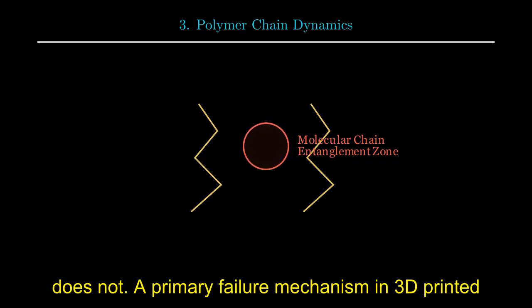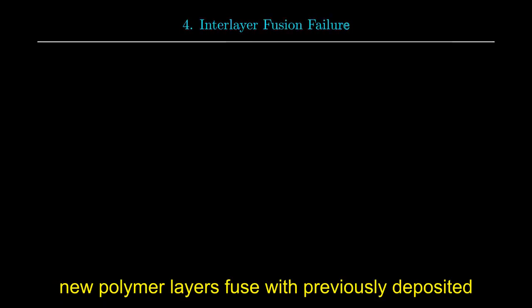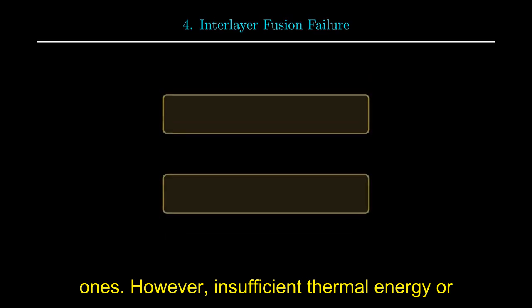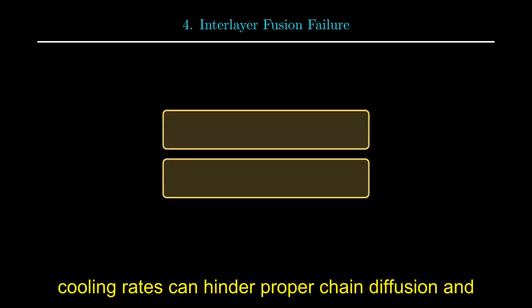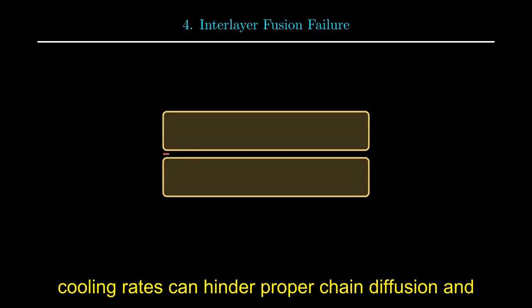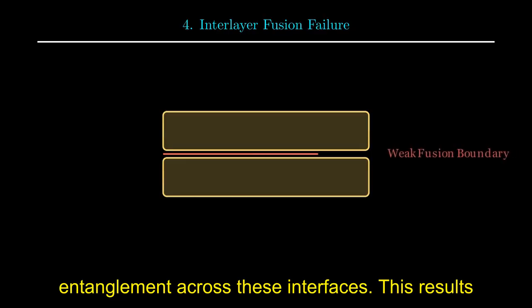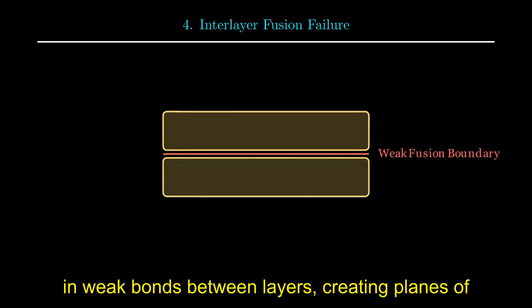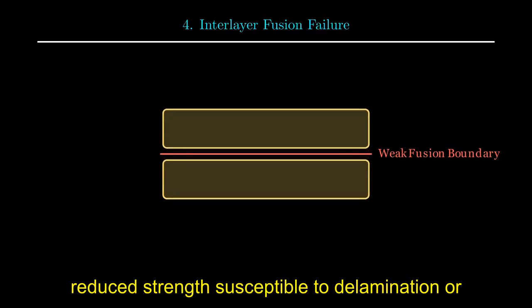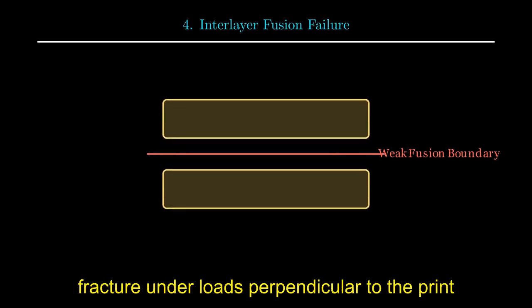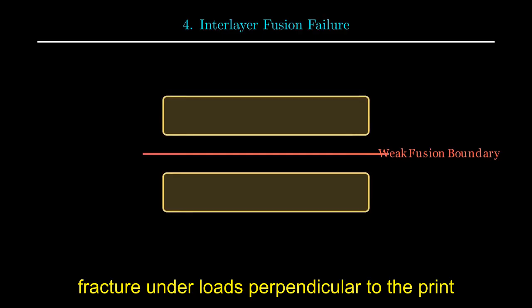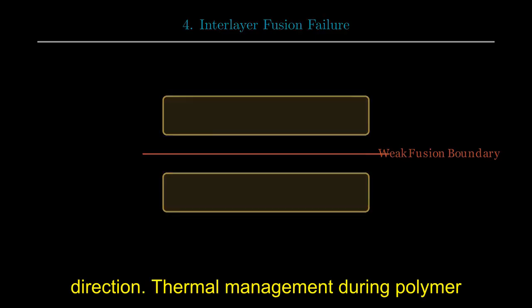A primary failure mechanism in 3D printed polymers is interlayer weakness. During deposition, new polymer layers fuse with previously deposited ones. However, insufficient thermal energy or cooling rates can hinder proper chain diffusion and entanglement across these interfaces. This results in weak bonds between layers, creating planes of reduced strength susceptible to delamination or fracture under loads perpendicular to the print direction.